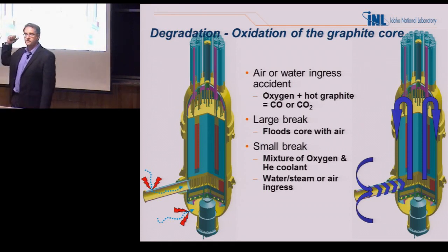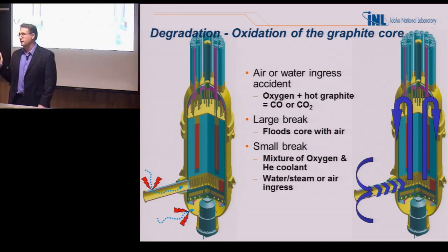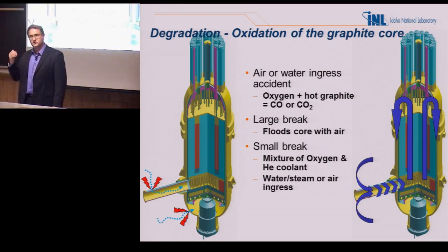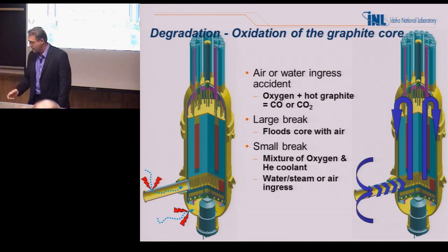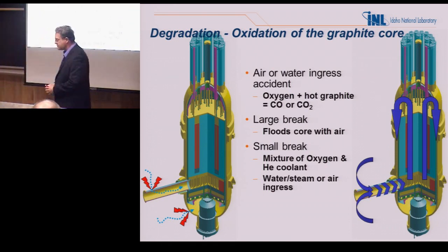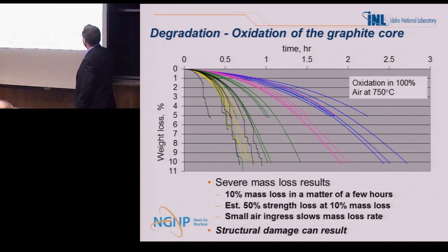For every single graphite reactor, you have water leaks. And they're small, and the graphite deals with it, but it's going to erode over time. So those are the types of issues. For a catastrophic acute event, you can see within a few hours at 100% air, there's no mixing of the helium or CO2 or anything else. This is the worst case scenario.